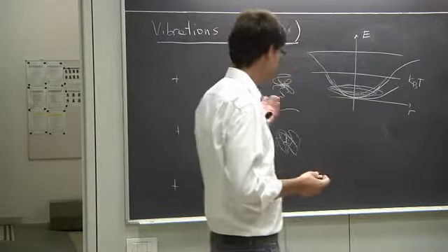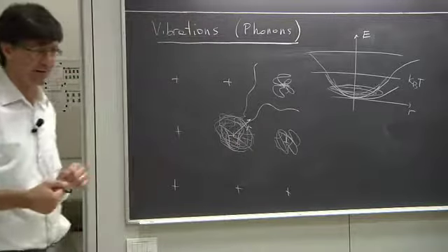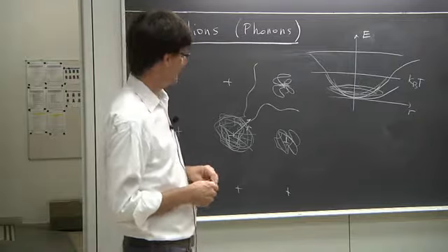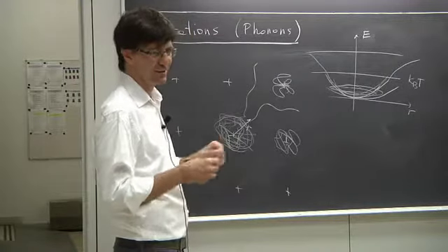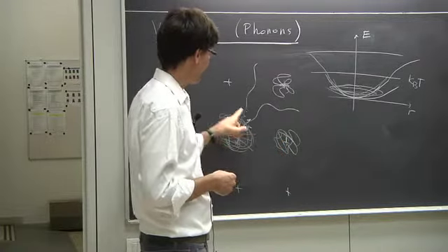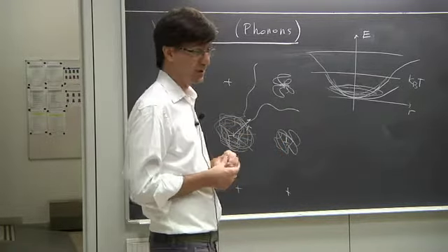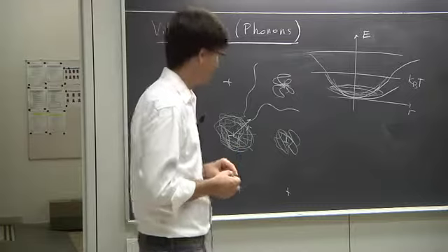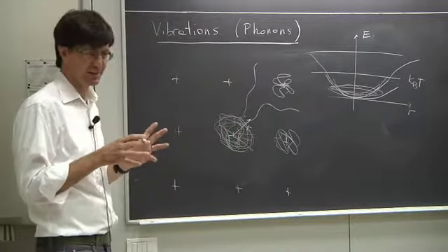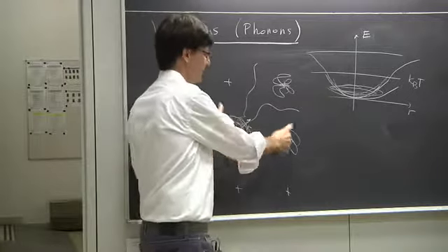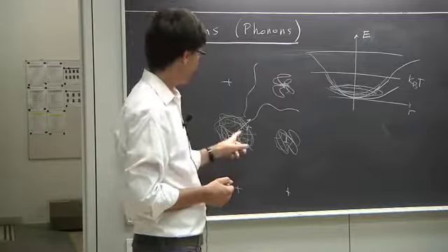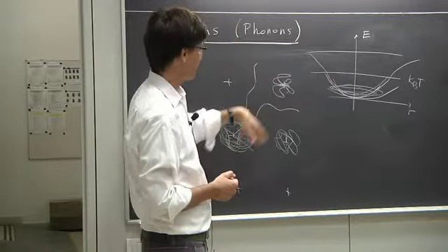Okay? In fact, there is even a rule of thumb, which is verified to an impressive precision, even though it's not a theoretical rule. And that rule states that as soon as the averaged amplitude of the vibration around the nucleus exceeds something between 15 to 20% of the distances between atoms, then the particle will begin to diffuse freely.